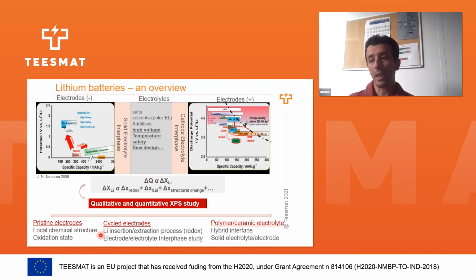During cycling, we can probe the lithium insertion and extraction through the redox process, or the solid electrolyte interface growth. Or nowadays, with the growth of all-solid batteries, for example, it can help to understand the interface in hybrid electrolytes like polymer-ceramic, or the interface between solid electrolyte and electrode. And in all those cases, we need to have very careful sample manipulation.